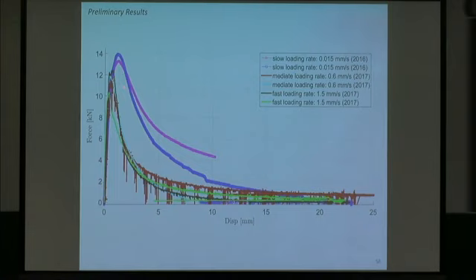Then we tried to do it faster with the intermediate loading rate, which is 40 times larger, and then again 100 times larger. And we see that as we go to higher speed, the load peak is decreasing a bit, but it's not always the same, because we see an anomaly here with fast loading, this dark curve. This dark curve is a bit higher together with this intermediate loading, so they are a bit inseparable.